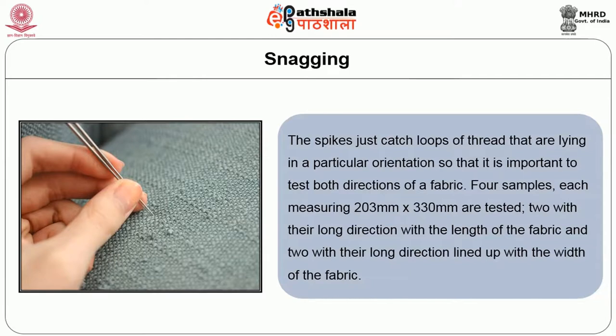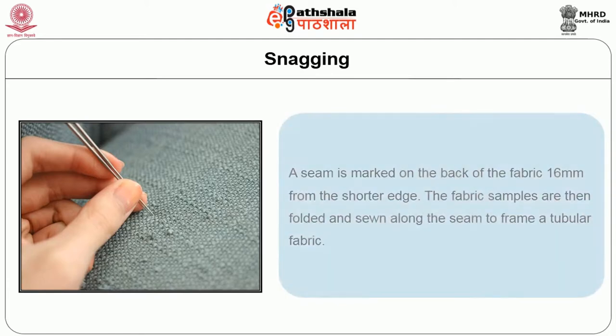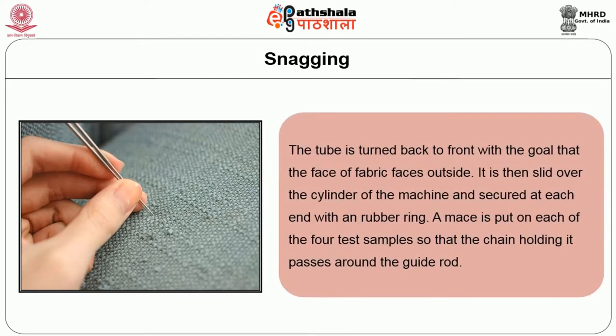The sample dimension here is 203 mm by 330 mm, two with the long direction along the length of the fabric and two with the long direction lined up with the width of the fabric. A seam is marked on the back of the fabric 16 mm from the shorter edge. The fabric samples are then folded and sewn along the seam to form a tubular fabric. The tube is turned back to front so that the face of the fabric faces outside, as it is in the case of the pilling test.